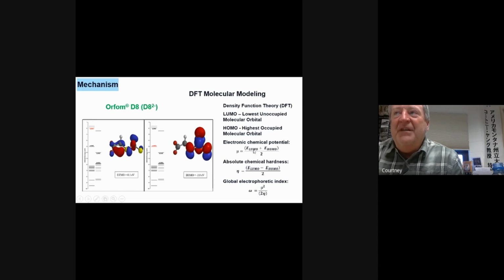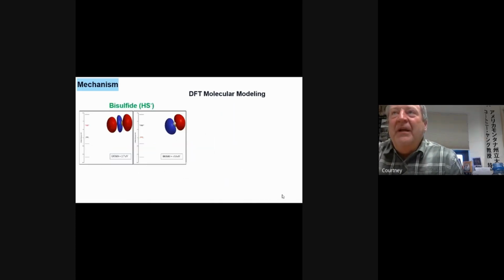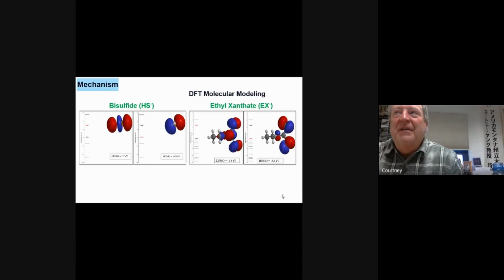Anyways, once we have these energy values, we can calculate what we call the electronic chemical potential, mu, the absolute chemical hardness by this formula, eta, and then the global electrophilicity index, which is this squared divided by 2 eta, and we end up with omega, the global electrophilicity index. And then we're going to put these all in the table. And we're going to compare it to bisulfide, and we're going to compare it to ethyl xanthate. We're going to just do the exact same thing.